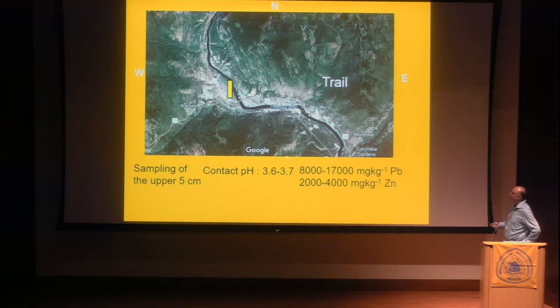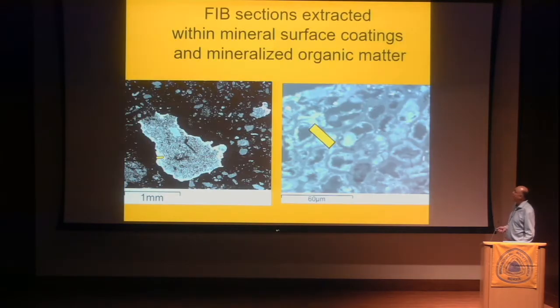The soils are quite acidic, with a pH of 3.6, 3.7, and we have up to 17,000 milligram per kilogram lead and up to 4,000 milligram zinc. So we took a focused ion beam section from a mineral surface coating shown here. The section was taken from there, and we took a FIB section from confined pore spaces, or long confined pore spaces, in a mineralized organic matter.